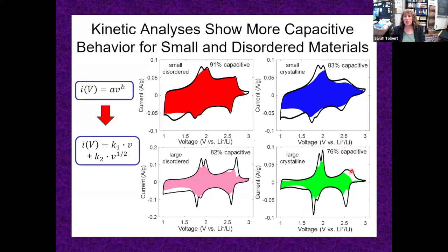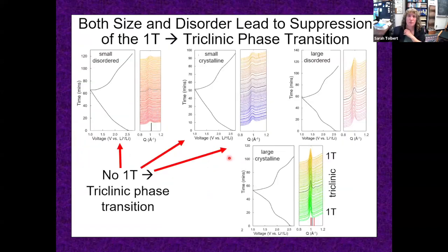And what we see is there is the most white on the things that are large and crystalline. There is the least white on the things that are small and disordered. So this is 90% capacitive. This is 76% capacitive. And then again, we see that things that are small and crystalline or large and disordered have about the same amount of white, and they're both about 80% capacitive. So size and disorder can equivalently make things charge faster.